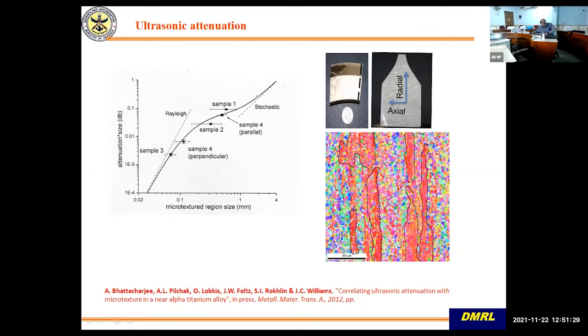And this kind of material in which you have elongated grains, if you send the ultrasonic signal in this direction, from top to bottom, again the ultrasonic signal attenuation jumps. If you send the signal in a parallel direction to this, then attenuation is much higher, because this is showing higher microtexture region in this region. So you can segregate the material based on microtexture. That is, random microstructure, as I told you, will have higher fatigue life and higher dwell fatigue life.